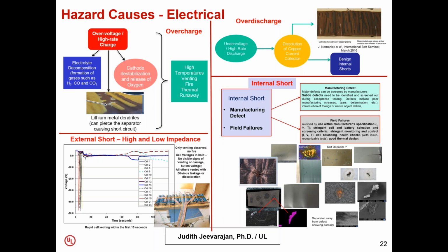So quickly going through the electrical hazards, the first one I'll mention is the overcharge. This is when you have a high voltage or over voltage or a high rate charge. You can have electrolyte decomposition, cathode destabilization, lithium dendrite formation, which then leads to high temperatures, venting, fire, and thermal runaway. When you have an over discharge, there are 2 things that can happen.